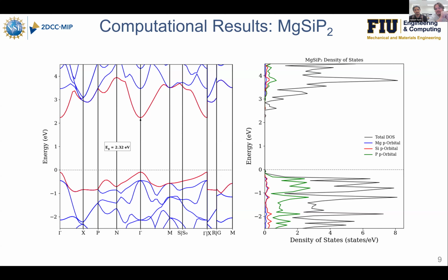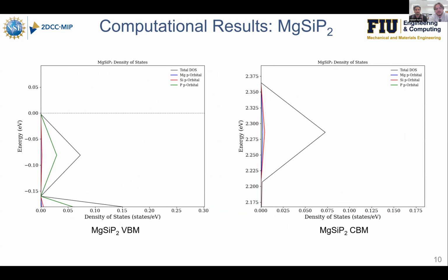And on the right, we have the density of states, the total density of states, and then also broken down into the major orbital contributions from each of the individual atoms. And it's a little hard to see exactly the valence band and the conduction band, so I have them zoomed in here on the next slide. And we can see that the major contributor in the valence band is the phosphorus p orbital. And meanwhile, the conduction band has slight contributions from all of the ones listed, but for the most part, it's the silicon p orbital and the magnesium p orbital.